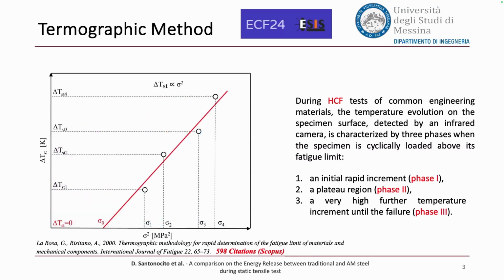Based on this consideration, the thermographic method consists of plotting the sigma squared and the delta temperature of stabilization, then drawing a linear regression, and the intersection between the x-axis and the linear regression will be our fatigue limit.